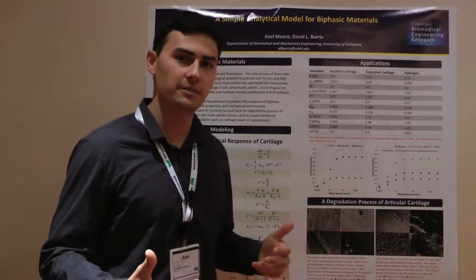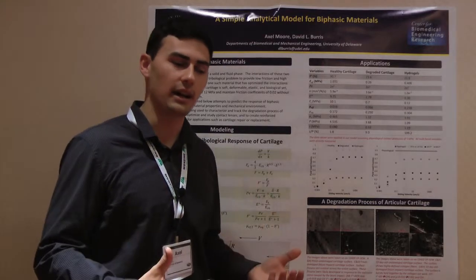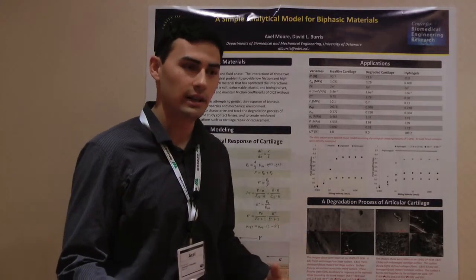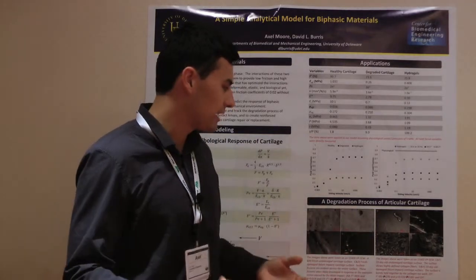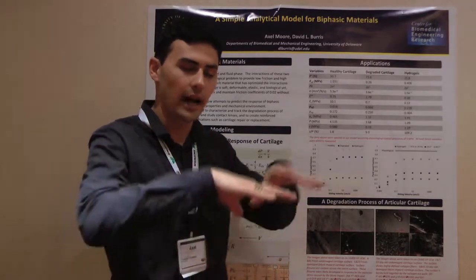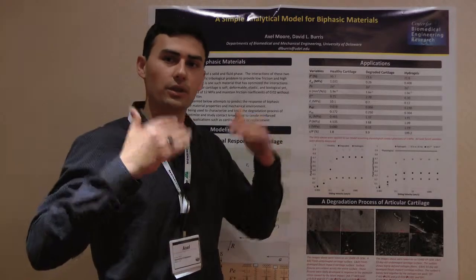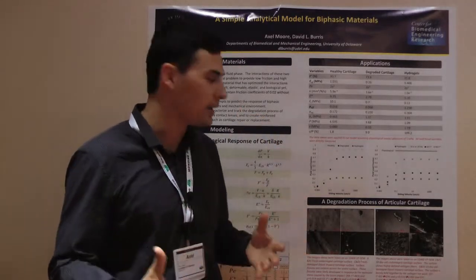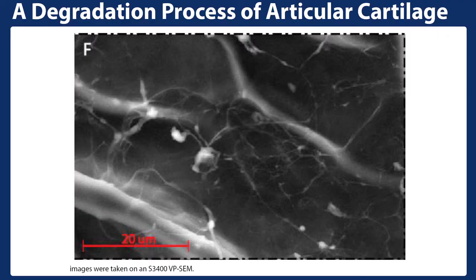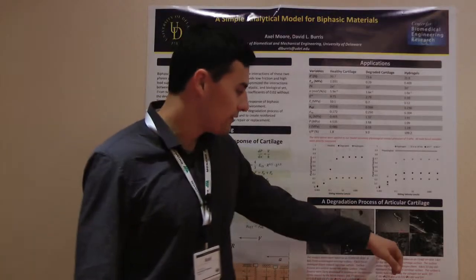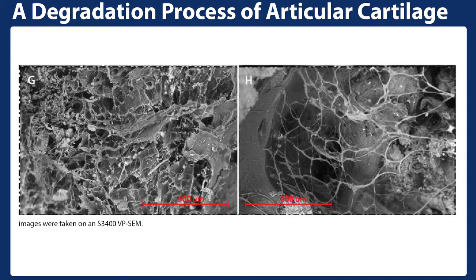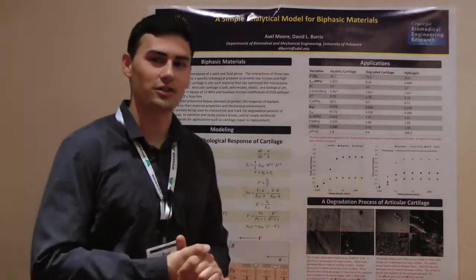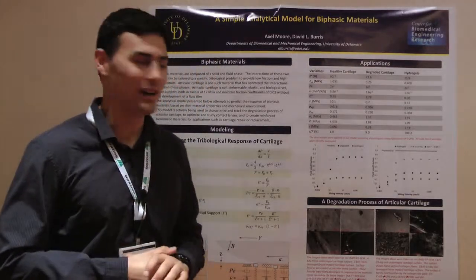For a biological breakdown process: because this is a biological material, it has cells that release enzymes which naturally break cartilage down. Over 33 days of a cartilage degradation process, you get pronounced collagen fibers showing up in the top layer. This increases friction, but more importantly decreases fluid load support, transferring load to the solid matrix. You can really see the defined collagen fibers — like rope structures — in the zoom. If you then apply a blunt impact injury to this already degraded cartilage, you turn it into pulp. That's essentially what my poster shows — this model for osteoarthritis and hydrogel design.